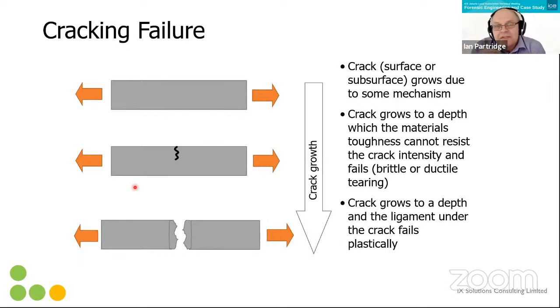The other thing that happens is that there's two mechanisms when it comes to cracking. One's the crack trying to drive forward. The other is the remaining ligament, a bit like metal loss, where you can imagine it like metal loss, it's just overloading of the remaining ligament.